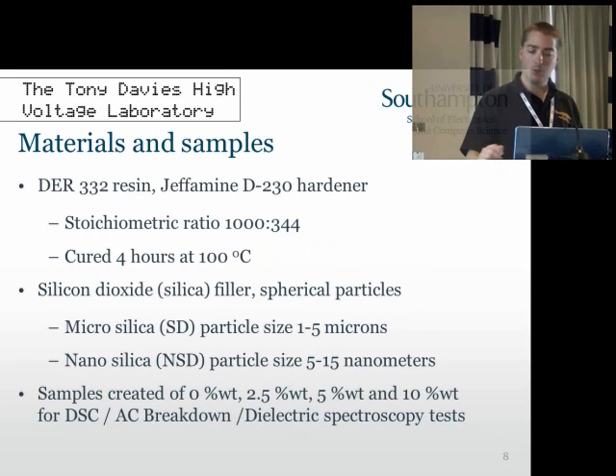So what we've taken is a standard DER 332 resin. We've used an amine Jeffamine D230 hardener. We've calculated the chemical ratio, which here is 1000 to 344. And we've taken a standard curing of 4 hours at 100 degrees.